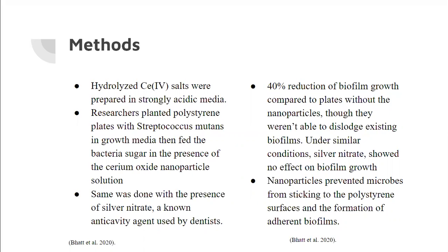There was a 40% reduction of biofilm growth compared to plates without the nanoparticles, though they weren't able to dislodge existing biofilms. Under similar conditions, silver nitrate showed no effect on biofilm growth. Nanoparticles prevented microbes from sticking to the polystyrene surfaces and the formation of adherent biofilms.